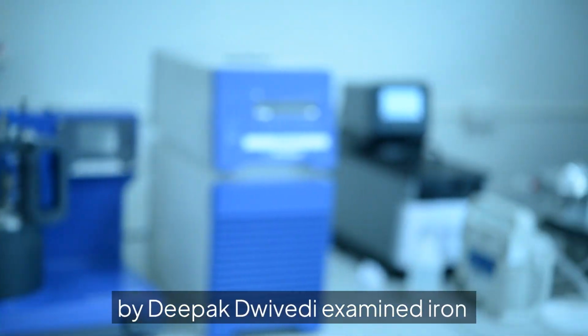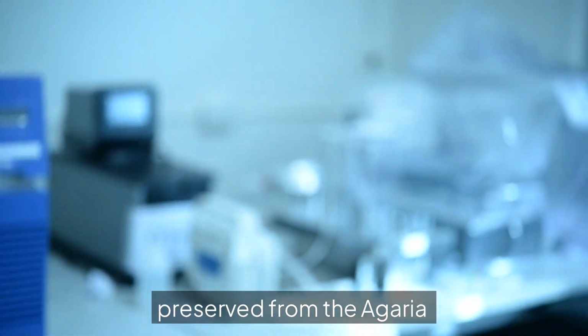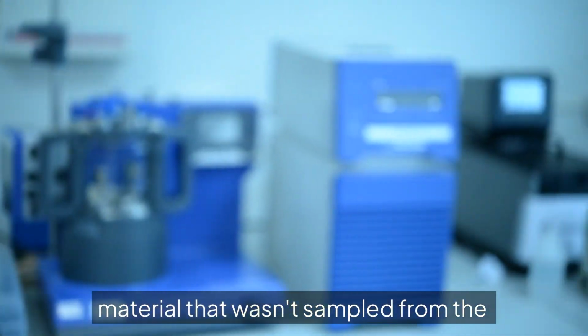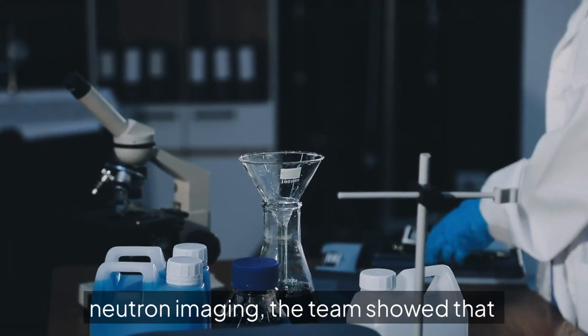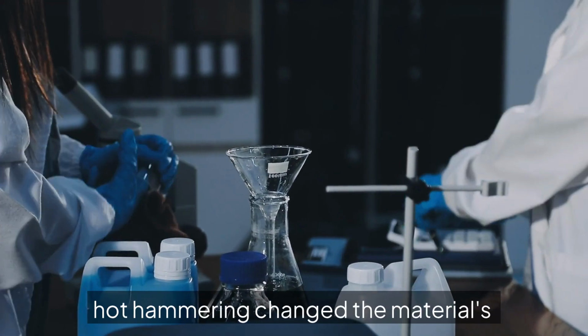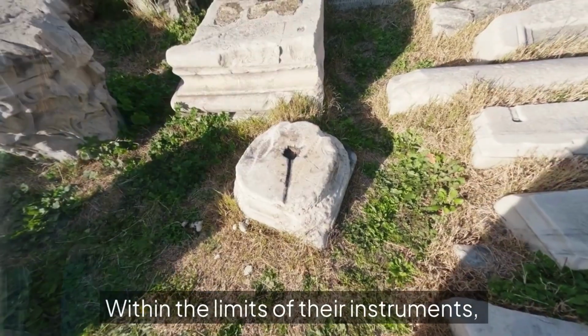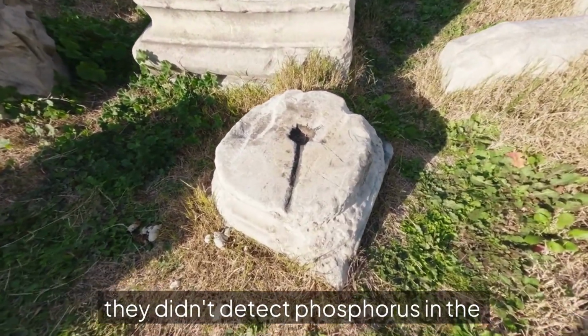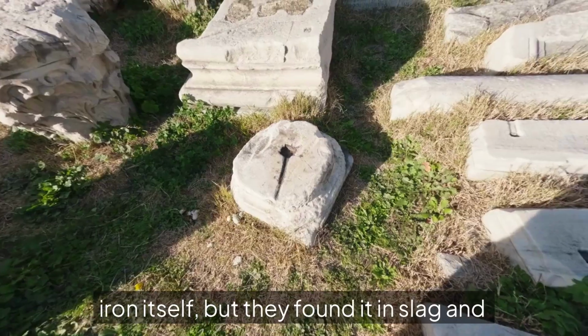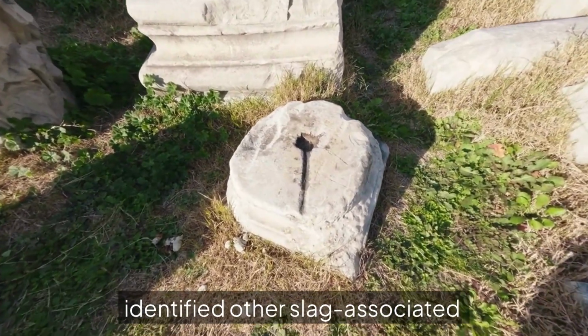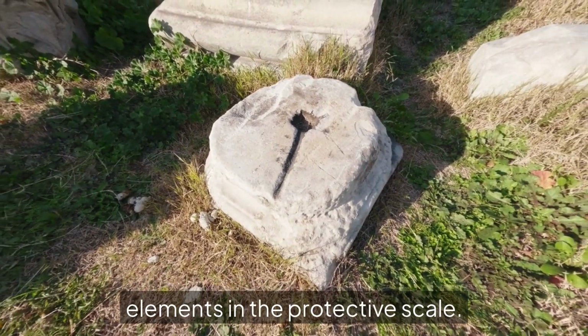In 2021, a Scientific Reports team led by Deepak Trivedi examined iron preserved from the Agaria metallurgical tradition in central India, material that wasn't sampled from the Delhi pillar itself, and that distinction matters. Using microscopy, spectroscopy, and neutron imaging, the team showed that hot hammering changed the material's pores and corrosion film. Within the limits of their instruments, they didn't detect phosphorus in the iron itself, but they found it in slag and identified other slag-associated elements in the protective scale.